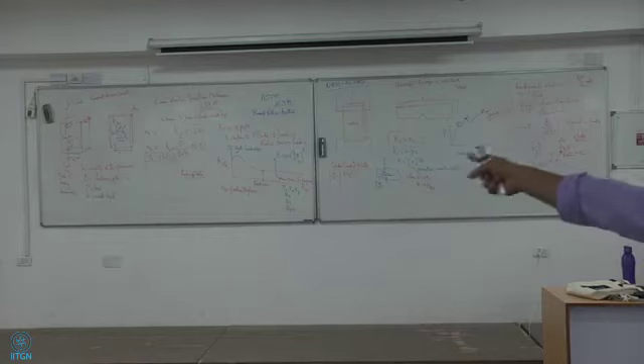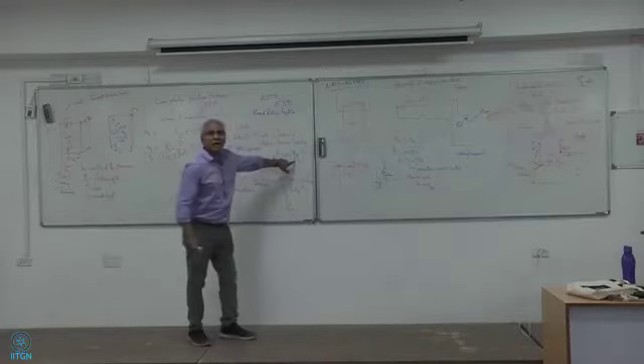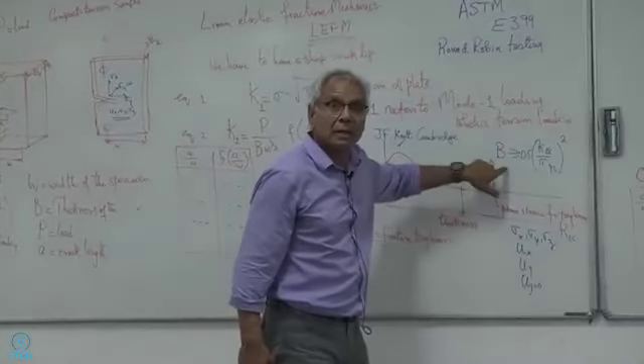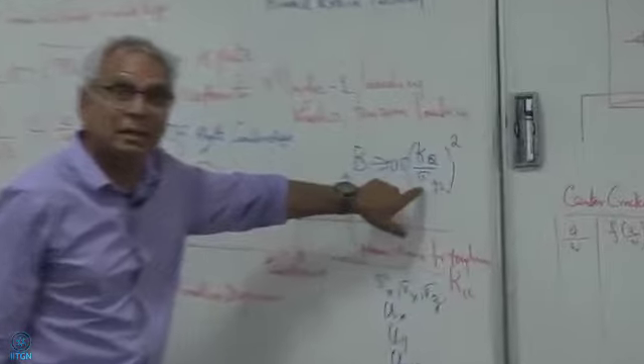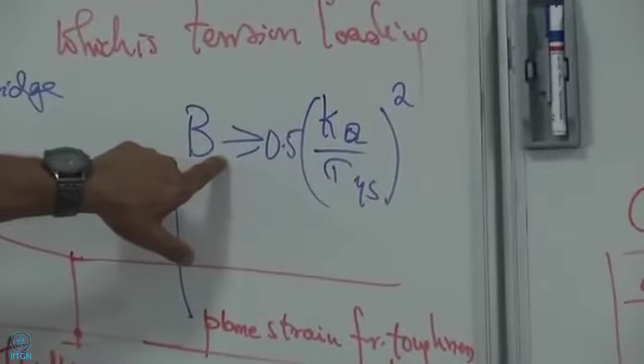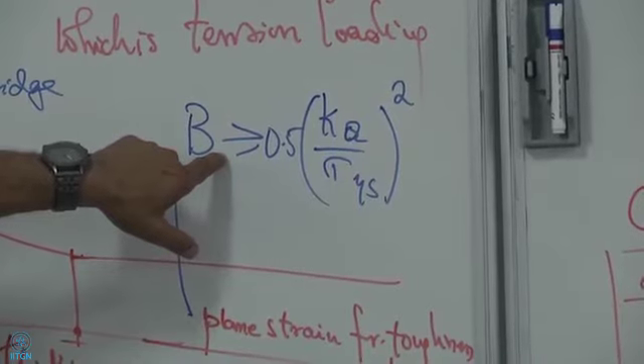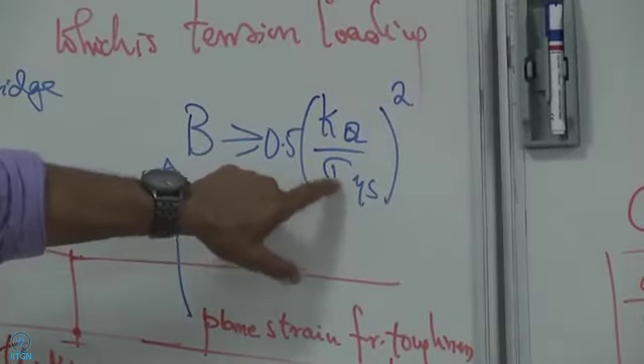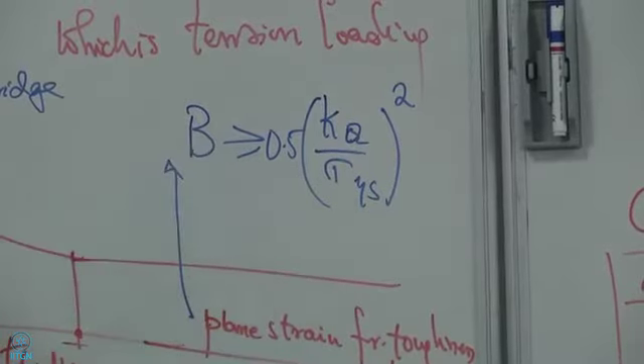So if your yield stress is low, your B will be high. Can you see from there what I'm writing? Okay. So if this is high, this is low. If this is low, this is high. So if you have a low yield stress material, it's very tough to meet the plane strain condition, right? If you're testing high strength materials, it's much easier to meet the plane strain condition.